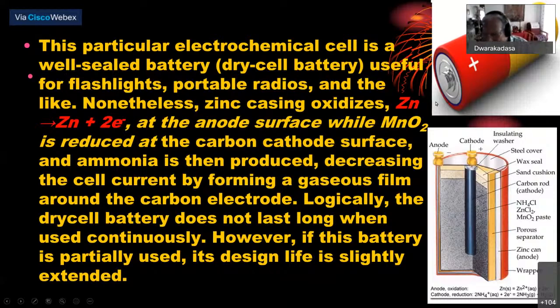Although it appears it can keep on going continuously, there is this limitation: the zinc casing is oxidizing at the anode surface, while the manganese oxide is reduced at the carbon cathode surface, and ammonia is then produced, decreasing the cell current by forming a gaseous film around the carbon. So this logically sets a certain life for the cell, and therefore the cell does not live forever. It has a limited life.